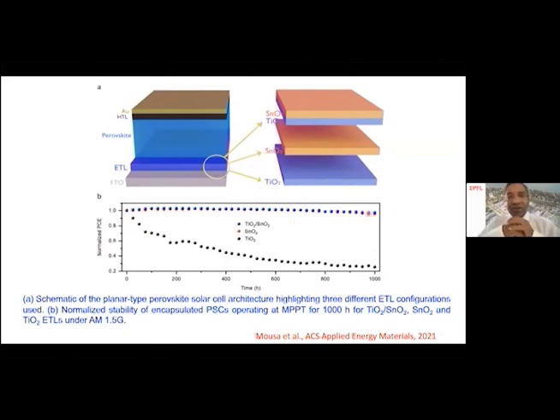Now the question is why this is happening. When we use pure TiO2, TiO2 is a photochemically very active material. Remember this point, photochemically very active, and it gets excited and it starts eating the perovskites. Therefore, pure TiO2 as an ETL layer is damaging the interface. So now by having this type of interlayer, tin oxide, between the TiO2 and perovskite as a buffer layer, you can increase the stability significantly without damaging your main interface.